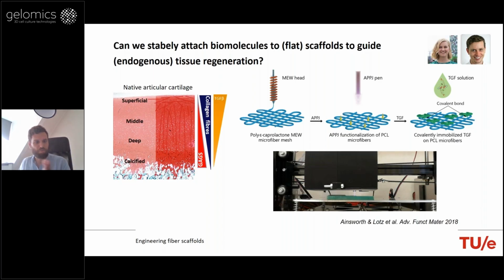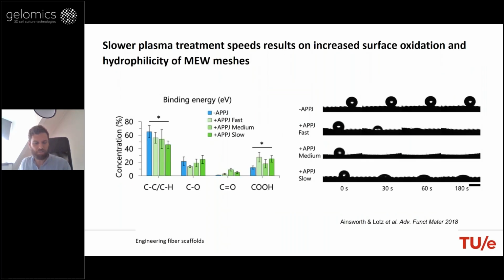It was very interesting to see. We explored different conditions, and I will walk a bit faster here. We tested different conditions of functionalization. So basically, we had the plasma pen passing over the scaffold at different speeds, so a fast, a medium, and a slow. And then we looked at the oxygen-containing groups that were present at these different speeds, and we related this to the wettability of the material.